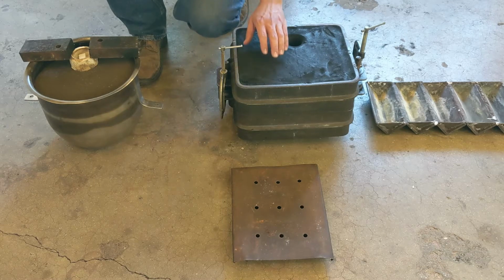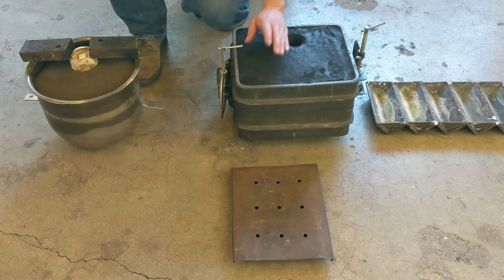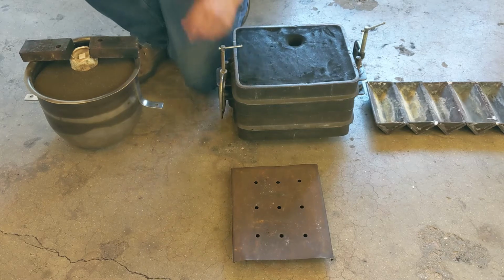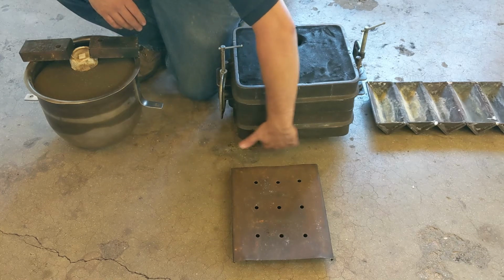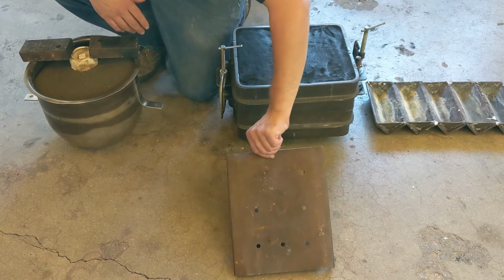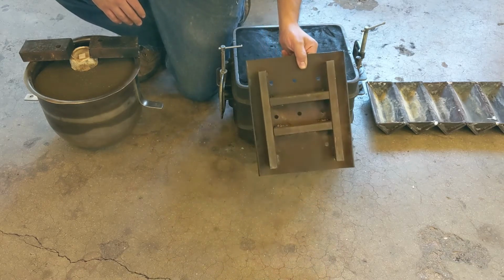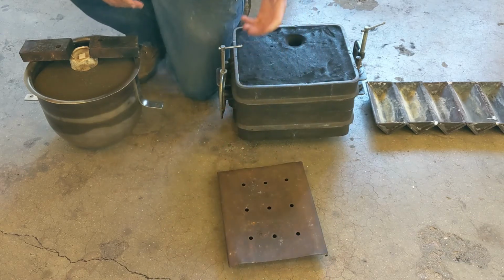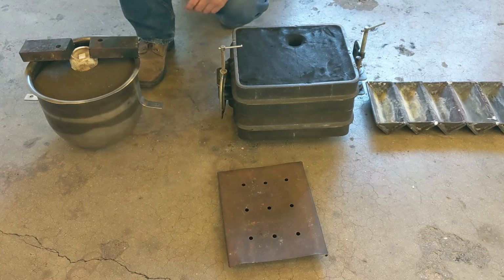As well, when we fill this green sand mold with metal, the hot metal is going to drive back a layer of water vapor as it evaporates the moisture that's closest to the part cavity. And when that moisture starts to pass through the permeable molding media, we want to give it lots of opportunities to off-gas and to escape. So underneath the green sand mold, you'll see that I've added this perforated bottoming board. And the bottoming board just serves to keep the mold off the concrete so that that moisture can escape.